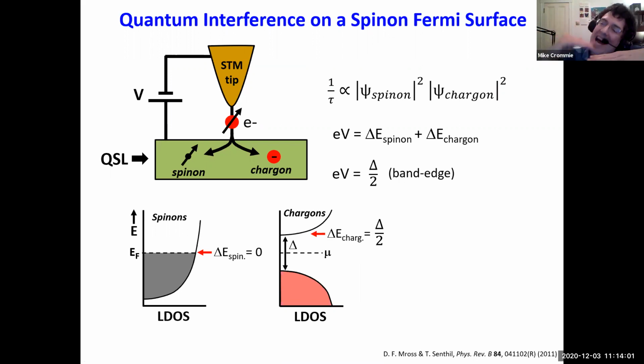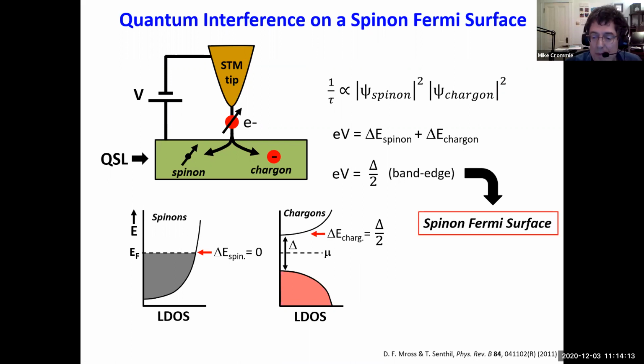So if you're right at the edge of the gap, all your energy has to go into the chargon, and that leaves nothing left for the spinon. But the spinon is still there, so that means that you have to have a zero energy spinon. Now, zero energy for the spinons is the Fermi surface. So if I'm tunneling electrons right into the band edge of the Hubbard band, then I'm probing the Fermi surface of the spinons. And so then I can image the spinon Fermi surface by taking images at the Hubbard band edge.